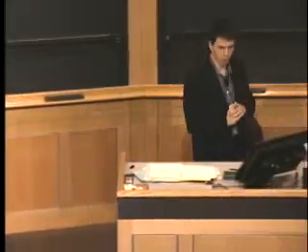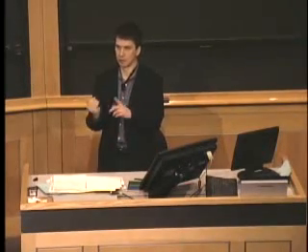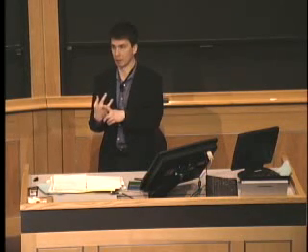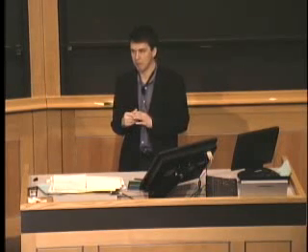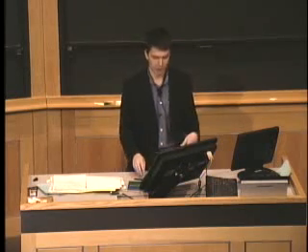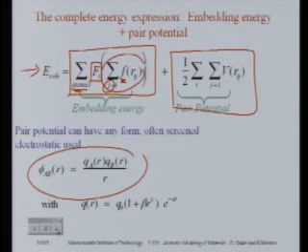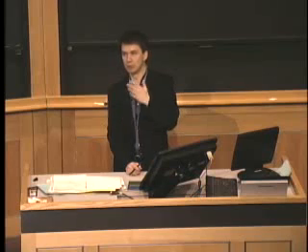So that means we have to solve three problems, really. The one we've solved: you need to know what the electron densities are. Take the Clementi and Roetti tables. You need to know what the embedding function is, and you need to know what the pair potential is. Okay. The pair potential used, to be honest, you can use almost anything. It's mainly used for the hardcore repulsion part. You don't want the atoms to fly into each other. Typically, they use some screened electrostatic form, which is essentially the product of charge distribution functions on atoms. But you know, nothing would stop you if you really wanted to from using a Lennard-Jones.